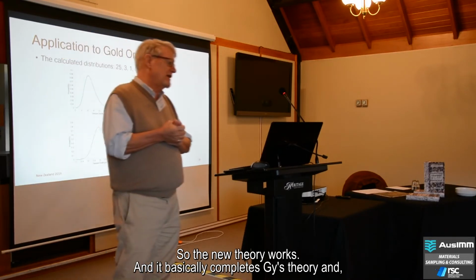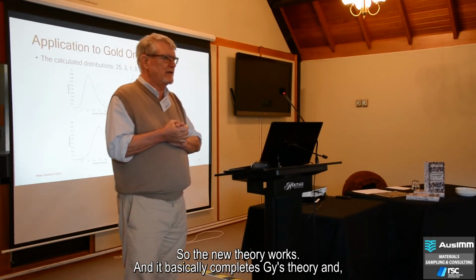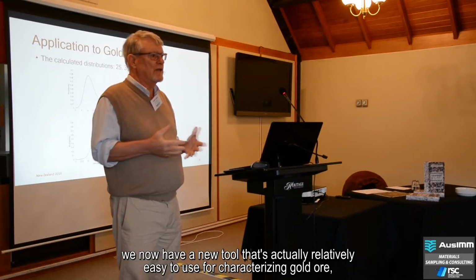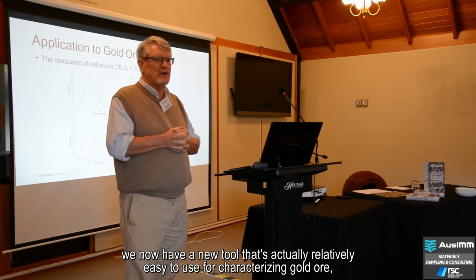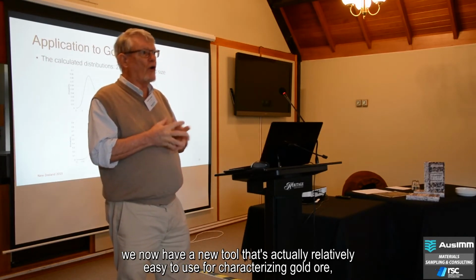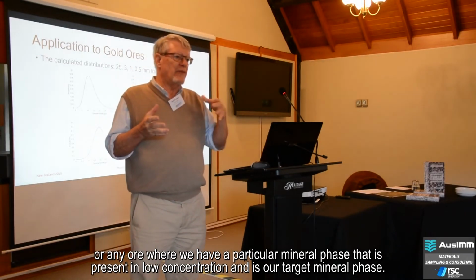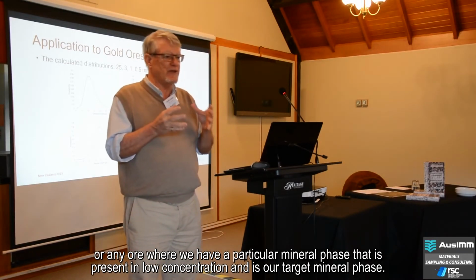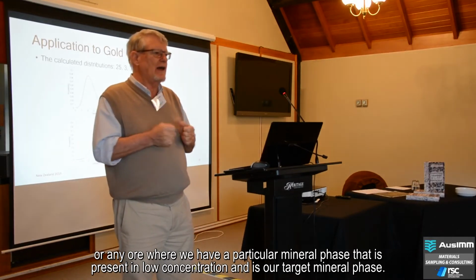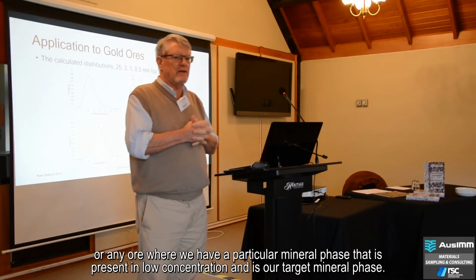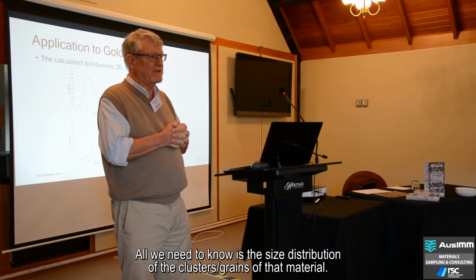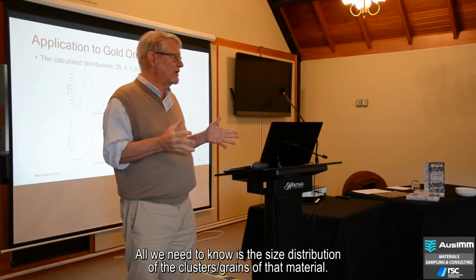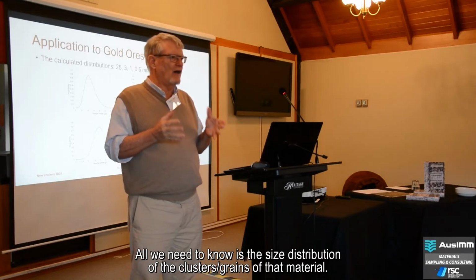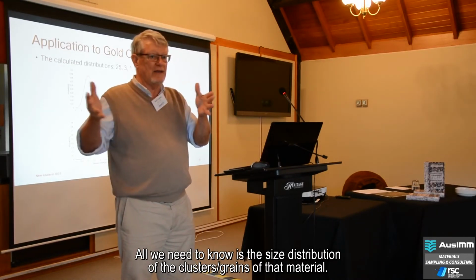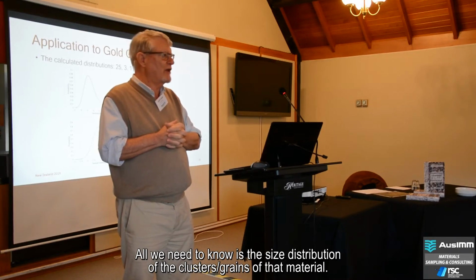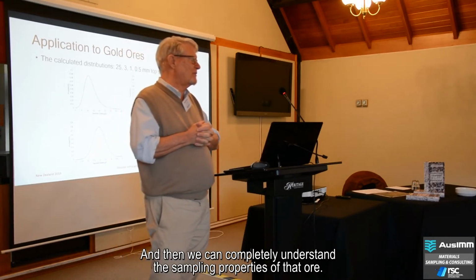And it basically completes Gy's theory, and we now have a new tool that's actually relatively easy to use for characterizing gold ores, or any ore where we have a particular mineral phase that is present in low concentration and is our target mineral phase. All we need to know is the size distribution of the clusters/grains of that material, and then we can completely understand the sampling properties of that ore.